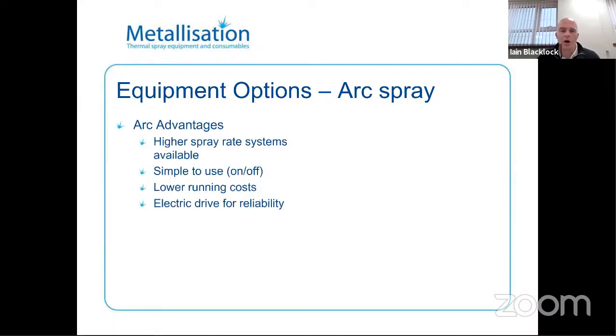So the advantages of arc: we can achieve higher spray rates subject to the amperage of the system, so considerably higher spray rates than the flame spray systems. It's simple to use. Generally, it's press a button, start spraying, pull the trigger, start spraying, finger off the trigger, push a button, and you've turned it off. When you compare coating costs, it's lower running costs for the coating, and with the electrical drive, it's a very reliable system.